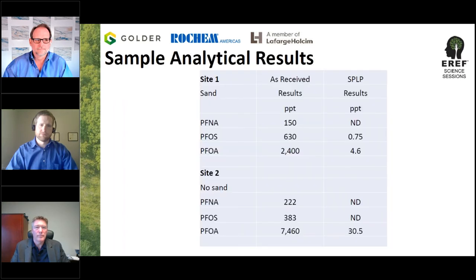Now, everybody gets excited about these three PFAS congeners. Obviously, there's a whole lot more of them, but the samples that we received had these levels that you see here, and you'll see one that says sand and one that says no sand. The reason I put sand in one of them is because I thought it would be helpful to give the binder something to bind to other than itself, and it allows you to use less of the binder than if you use no sand. With a no sand mix, the cementitious blend serves two purposes. It absorbs moisture and acts as a small aggregate, and then of course it's a binder as well.